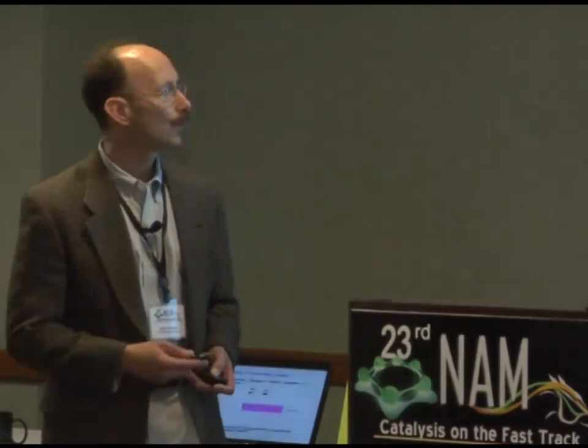Okay, now the problem that we're going to use just to illustrate what we're working on is this one of hydrogen purification using these copper-palladium alloy membranes. And the basic idea is that you have a gas stream, it has hydrogen in it and some other components. You want to separate out the hydrogen, and the way you do it is with a membrane that will absorb and dissociate the hydrogen, transport the hydrogen across the membrane, it recombines, and you end up with a purified hydrogen stream here and all the other junk going that way.